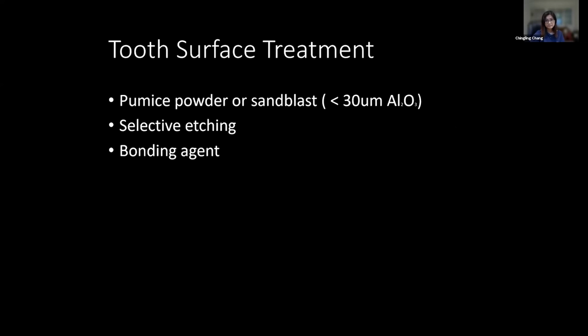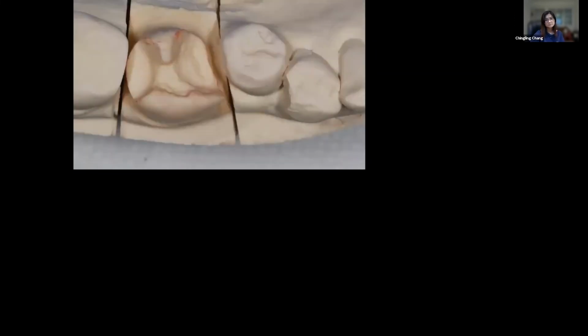And for the tooth surface, before we deliver the restoration, we can use pumice powder to clean the surface, or if you have a sandblast, it's more efficient. We can use sandblast to clean the tooth surface. And we do the selective etching, basically just on the enamel surface. And we apply the bonding agent on enamel. So like this inlay is being prepared. This is a tooth surface. We do the isolation, and we etch the porcelain, prepare the porcelain, and prepare the tooth surface, and after cementation. So there are a lot of procedures involved during cementation and it gets very critical. That's why bonded porcelain procedure is very technique sensitive.